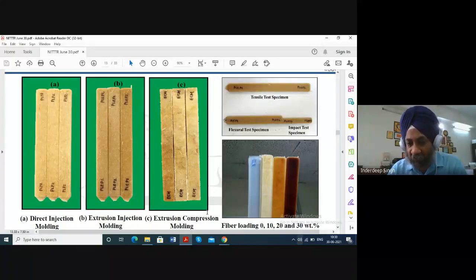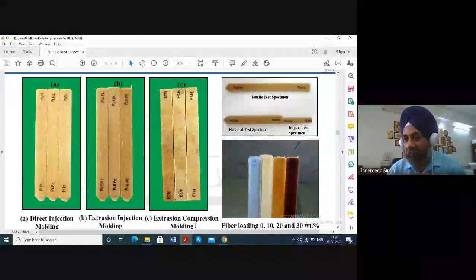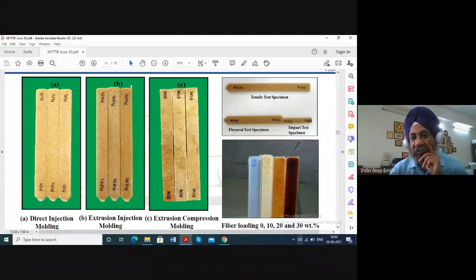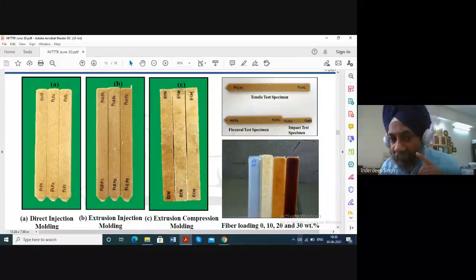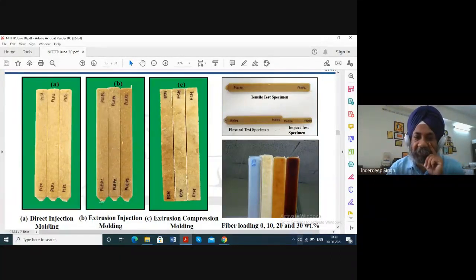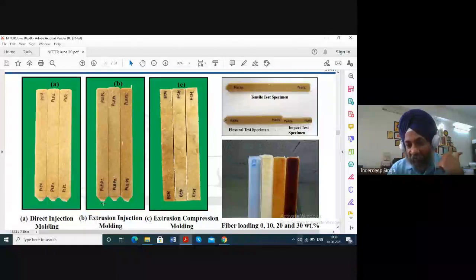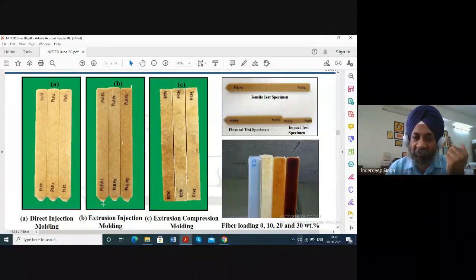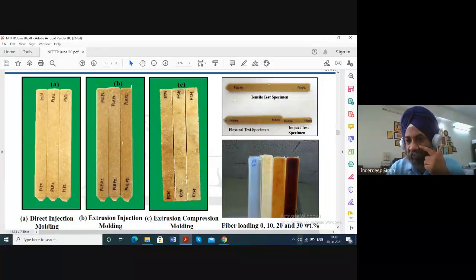So in extrusion compression molding, we are making a plate and then cutting the samples as per the ASTM standards. So you can see these are fairly rectangular samples, but the injection molded ones come from the injection mold where we get 3 samples in a single shot, and this is the place where injection takes place. On the other side of this we get the flexural and the impact samples. These are tensile testing samples shown here. So here you see a tensile testing sample, a smaller image, a flexural testing sample and an impact testing sample, the natural fiber based.